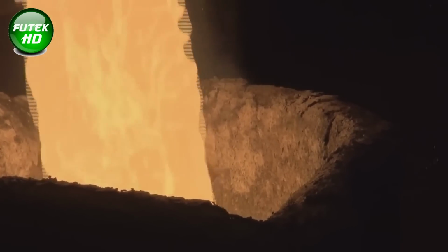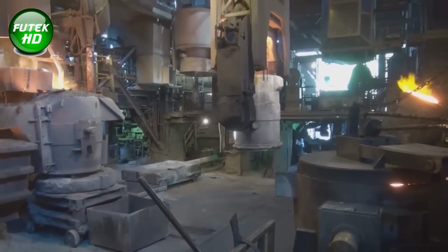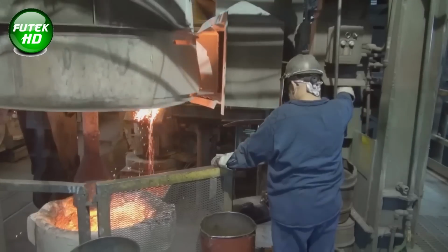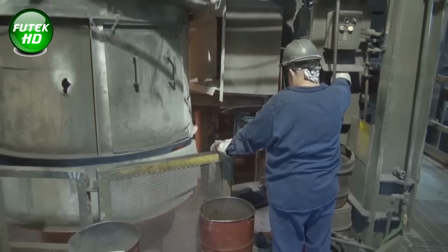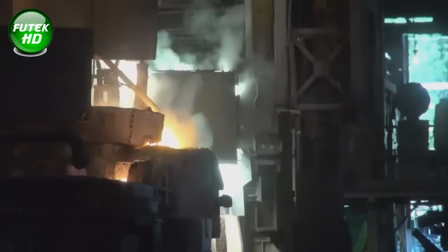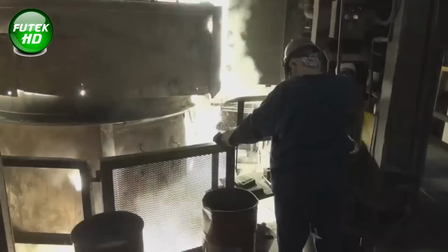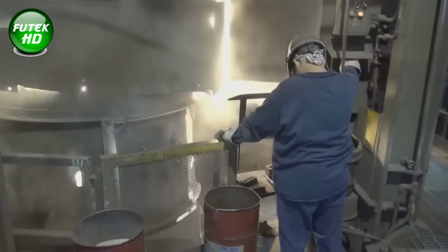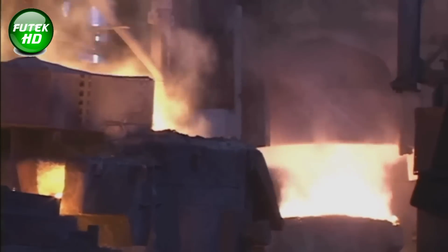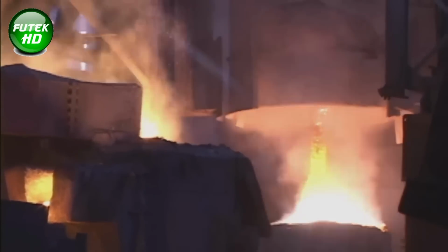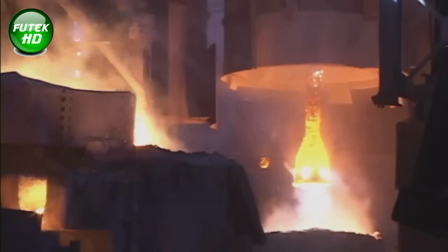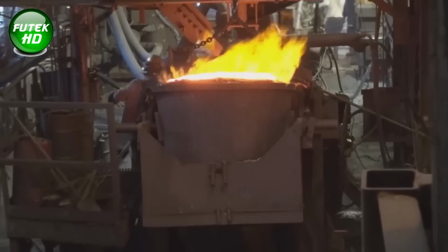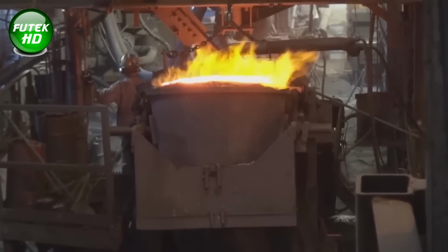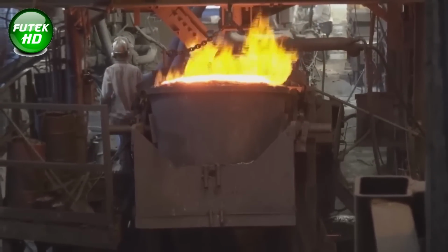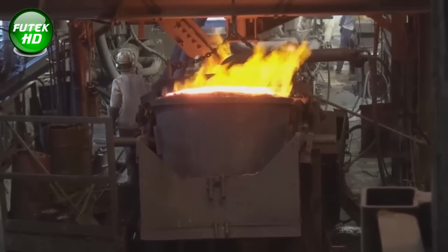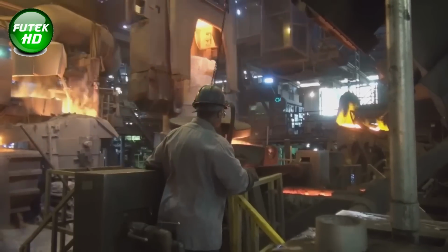As the scrap metal melts, it descends through the furnace, picking up carbon and sulfur from the coke. The molten iron exits the cupola through the tap hole, where it flows into a ladle. At this stage, desulfurization is performed to reduce sulfur content, a critical step for achieving the ductility needed in the final product. Lime is added to the molten iron, and the mixture is vigorously stirred to remove sulfur as slag. This desulfurized iron is then transferred to a holding vessel, where it undergoes further treatment, including magnesium addition, to prepare it for the next stage of production.